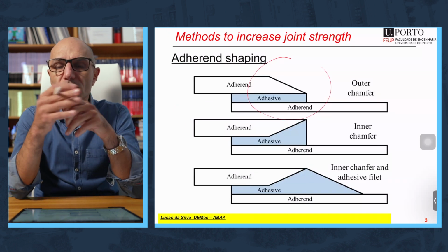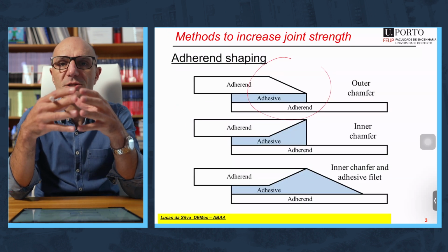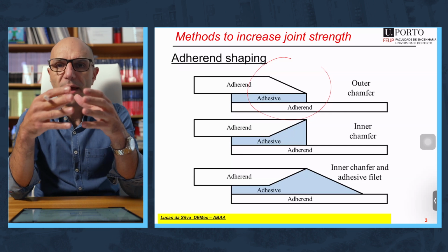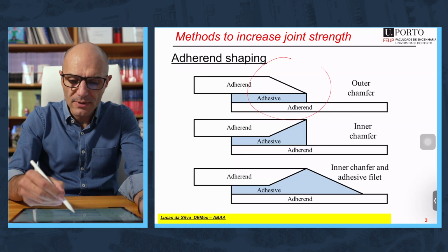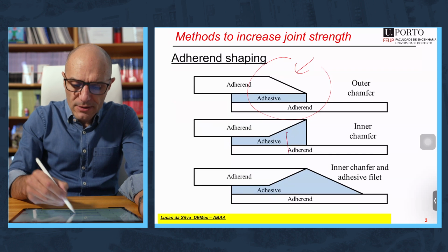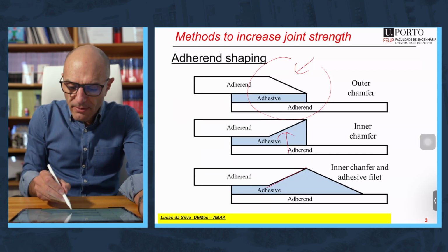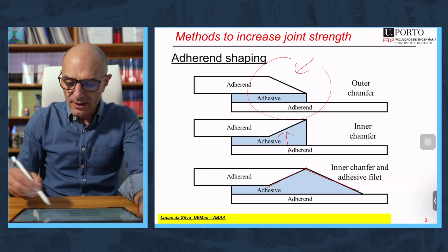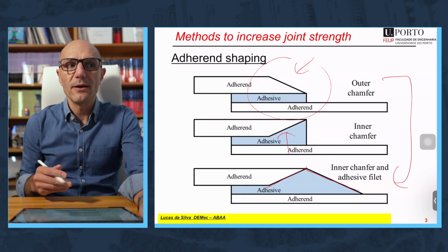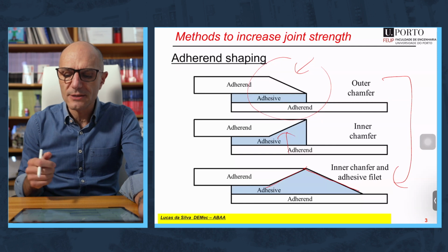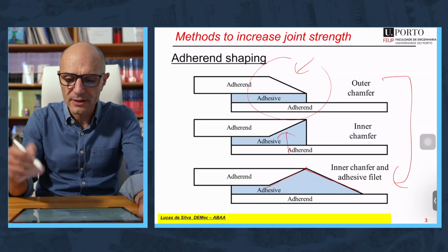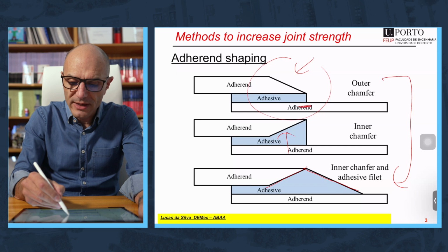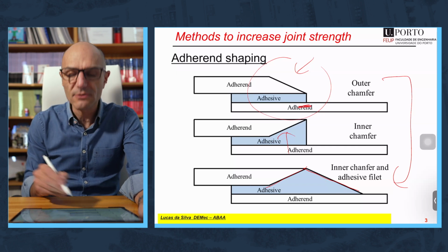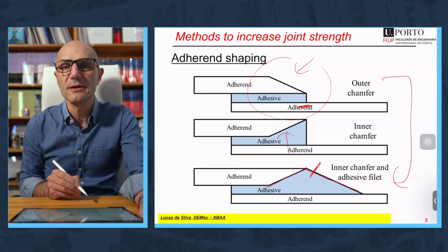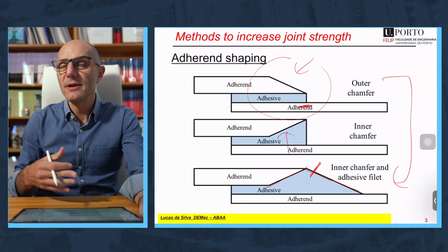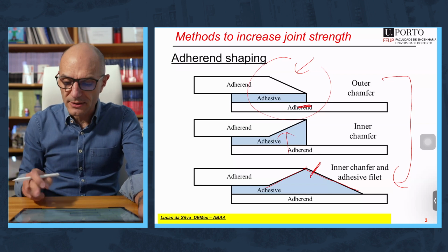You can also do that by changing the shape of the adherend and introducing a taper. It can be an external taper, an internal taper, or external taper plus spew fillet, which is even better. This can increase really 2-3 times the joint strength, especially if you talk about composite materials. With composite materials, with this situation, you might have a delamination. With this situation, it doesn't fail anymore in the composite, but fails somewhere here in the adhesive. And you can have really 2-3 times higher joint strengths.